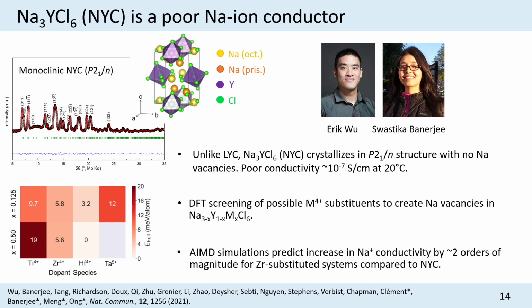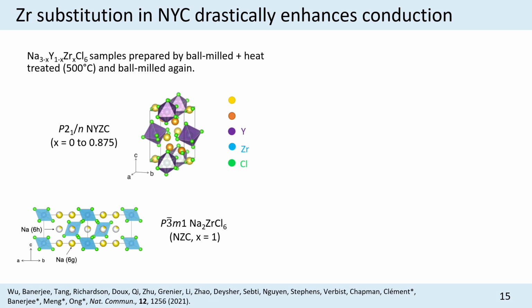We could synthesize them because the formation energy is not very high above the hull. And our ab initio molecular dynamics simulation suggested that zirconium substitution would increase the sodium transport properties by about 2 orders of magnitude. So the next step was to synthesize these yttrium zirconium chloride systems, and we made a whole series of materials from x equals 0 in this formula to x equal 1.